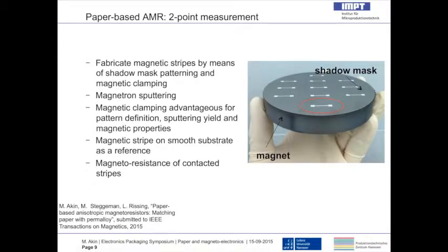As I said, we did the first experiments using 4-point contact resistance measurements. To validate those results, we used a different method for measuring electrical resistance. In the first method, we are able to avoid any resistances occurring through the contacts, soldering the wires, and so on. But in this method, we will be including those resistances, but measure the resistance not through touching the paper surface, so not applying a pressure on the paper, but through measuring through contacted wires.